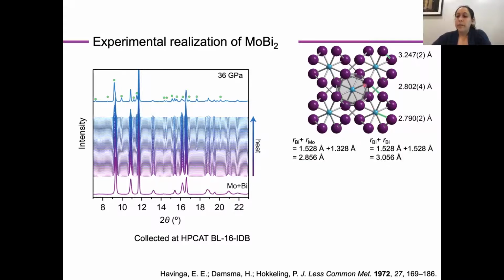Similarly, the bismuth distances are also quite important for getting this structure. And so you can see the sum of those radii down here. I compare it to the shortest bismuth distance here and the second shortest bismuth distance here. And so that I don't have to keep saying that, let's just call it D1 and D2 for the rest of the talk. You can see that D1 is quite a bit shorter than the sum of those metal radii, but D2 is quite a bit longer.